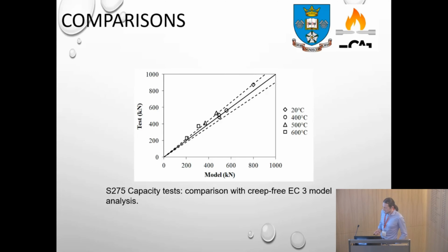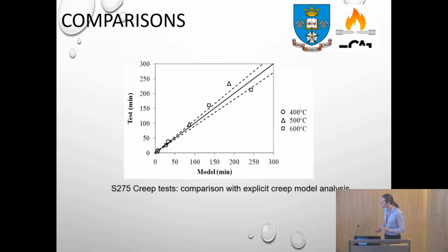So some comparisons. We did a verification study to see if the model with rotational spring is all right for modeling capacity tests. We also used the creep-free model that we proposed. And if you compare the model versus test for capacity tests in steel, you can see that the comparison is pretty good, which means that the model that we used for modeling the column behavior and the corresponding mechanical stress strain model is accurate enough for doing subsequent numerical studies. We also did an explicit creep model analysis, so I made a quasi-static model just to see if I can model the column failure time, which I obtained during the tests. And also the results seem pretty good, and we have some results on the safe side, which is pretty good, only one which falls on the unsafe side at 600 degrees.